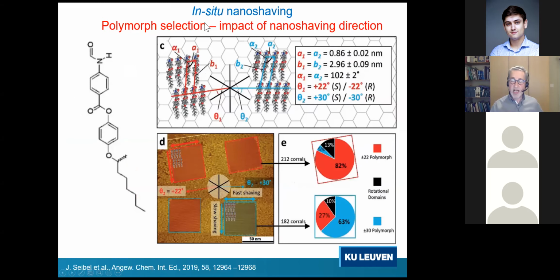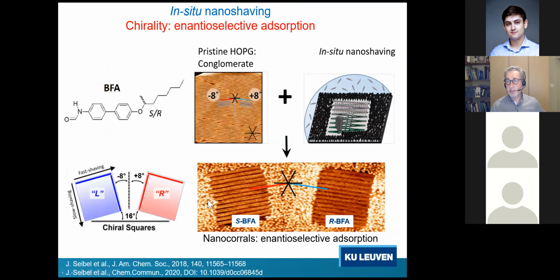I don't have time anymore, but in addition to polymorph selection based upon the size of the corals, we have also looked into the impact of the orientation of these corals with respect to the symmetry axis of graphite. And we can also selectively adsorb one of the polymorphs of this compound depending on the orientation of the corral with respect to the symmetry axis of the graphite substrate underneath.